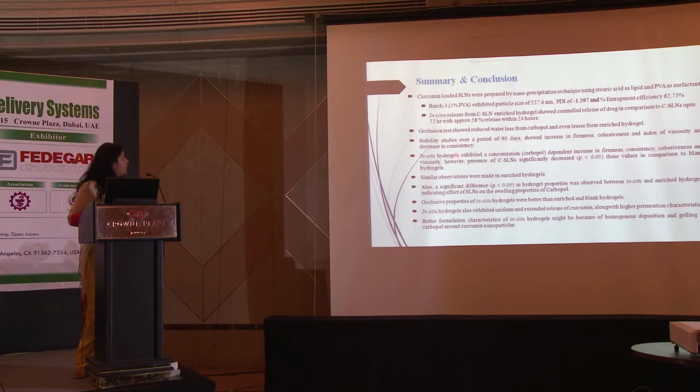Also it was found that in the case of in situ hydrogels, there was a concentration dependent increase in firmness, consistency, cohesiveness, and viscosity. Similar observations were made with enriched hydrogels. A significant difference in the hydrogel properties was observed between the in situ and the enriched hydrogels, indicating the effect of SLNs on the swelling property of the carbopol. We still need to perform further work on the antibacterial properties of curcumin, and this is the present state of our work.